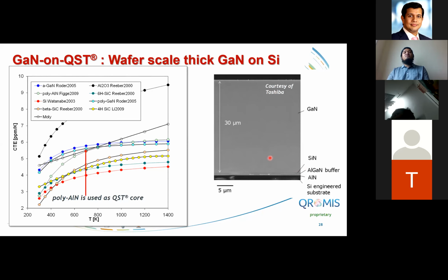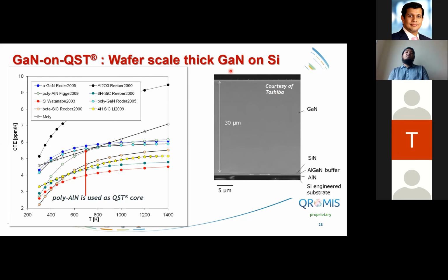On the right-hand side, we have one TEM courtesy of Toshiba, where we have the silicon substrate, and then their so-called engineered layers, the technology, an aluminum nitride core, and so on. And then we can see there's very nice, clean, crack-free 30 micron thick gallium nitride grown on this substrate. And as it happens, this can also be grown at 8 to 12 inch wafer scale. So we got pretty excited when we came to know about this technology.